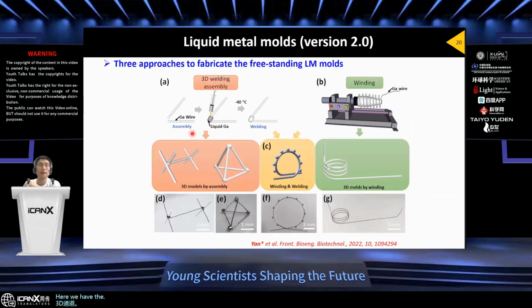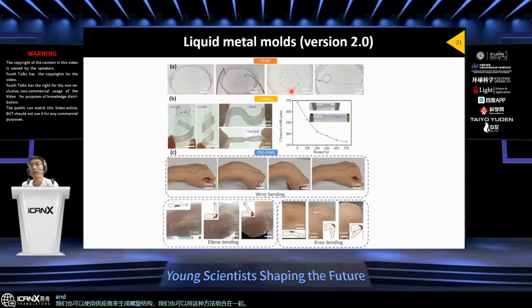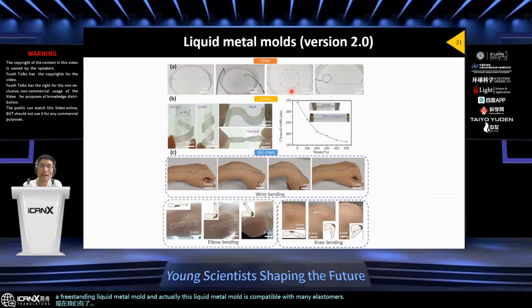Here we have three approaches to fabricate the freestanding liquid metal mold. The first one is the 3D welding assembly. We put the wires together, and with low temperature welding, we can have such kind of 3D molds. Also we can use the bender to generate such kind of spiral structure, and we can also combine these methods together. Now we have the freestanding liquid metal mold, and actually this liquid metal mold is compatible with many elastomers like PDMS, EcoFlex, and modified PDMS.